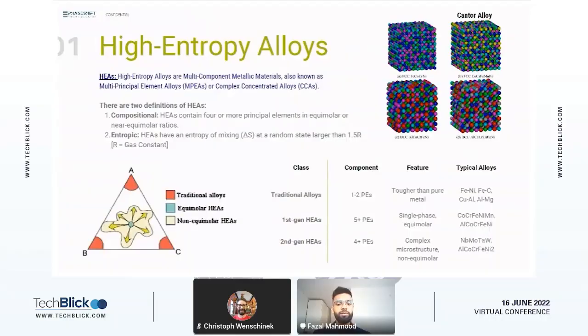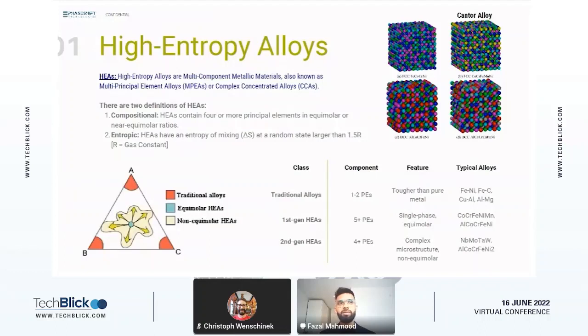So, high entropy alloys. High entropy alloys are a relatively new class of alloys that can have four or more principal elements in equimolar or near equimolar ratios. For this reason, they're also known as multi-principle element alloys or complex concentrated alloys. Different academics have some variation of the definition, but these two are most generally agreed upon. The other definition is the entropic definition — HEAs are alloys that have a high entropy of mixing, usually larger than 1.5R.